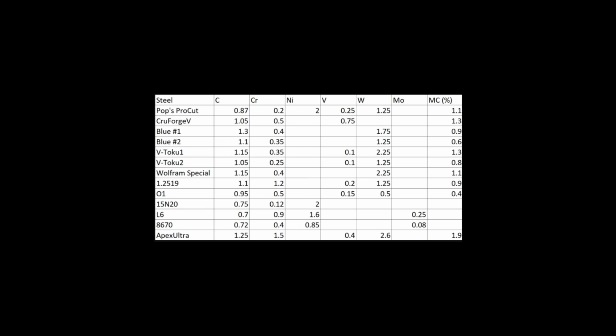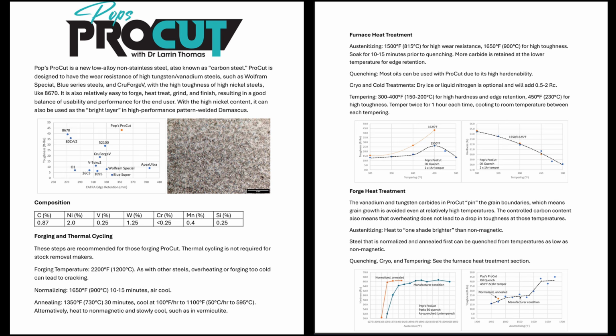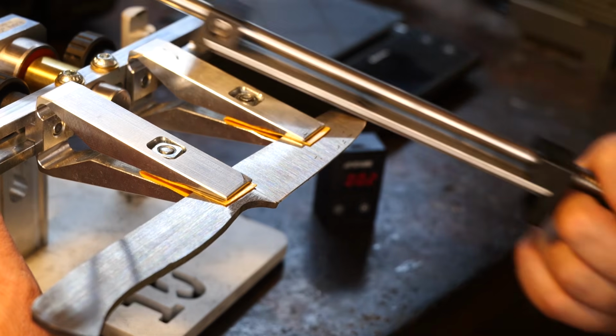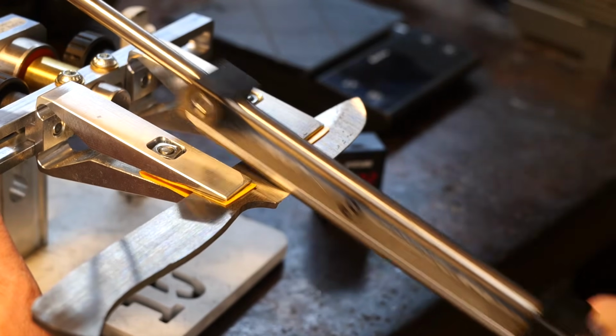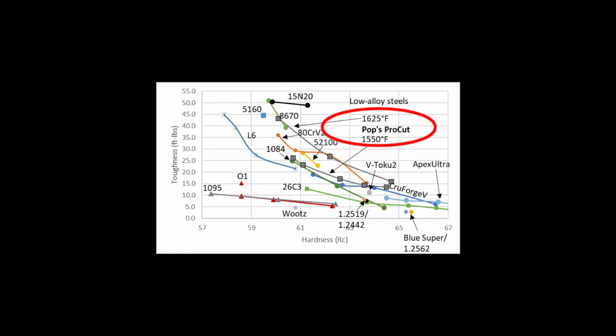Chemically, it's similar to 15N20, but it does add a fair amount of vanadium and tungsten. After forging, Larrin recommends a single normalization cycle followed by a fast DET anneal. Then ProCut can be quenched from 1500 degrees to 1650 degrees, depending on whether you're looking for better abrasion resistance and edge retention or a higher toughness. Since this steel hasn't been forged, it's straight from the producer, I'm going to just go straight to quench for testing. As you can see, ProCut is a bit less tough than 52100 when quenched from 1550 degrees Fahrenheit, but tougher than 52100, sort of in the 8670 range, when it's quenched from higher temperatures like 1625 degrees Fahrenheit.